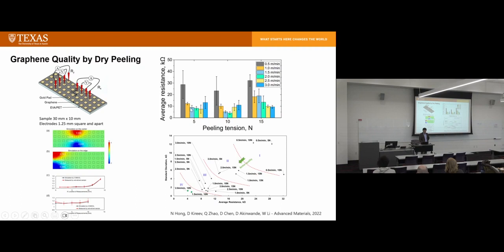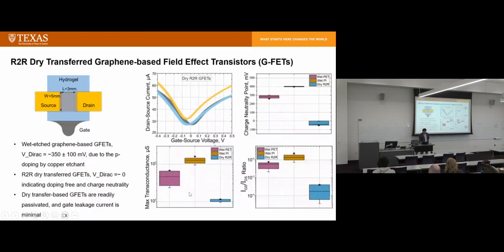The lowest resistance, or the highest quality we have been able to get, was when we use 10 Newton peeling. Of course, this is just a process parameter based on the sample size. So around 10 Newton and 2 meter per minute peeling speed. We're not only looking at average resistance, we'll also look at the standard deviation, and then you can plot a Pareto chart and figure out which conditions are the best. We want to have average resistance as low as possible, which indicates higher graphene quality, and also the variations as low as possible. So in the end, we decided to use 2 meter per minute and 10 Newton as our best parameter to give us quality.